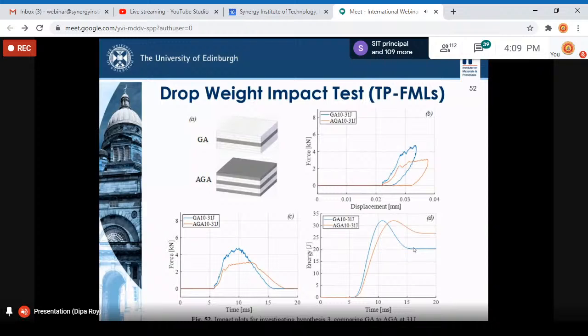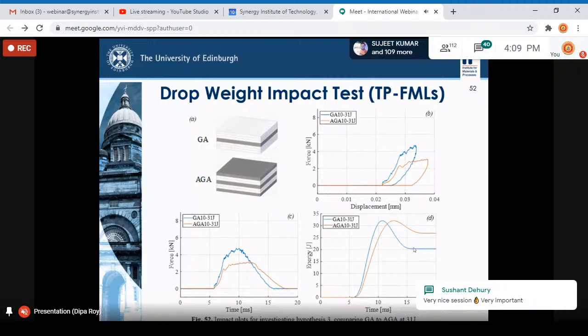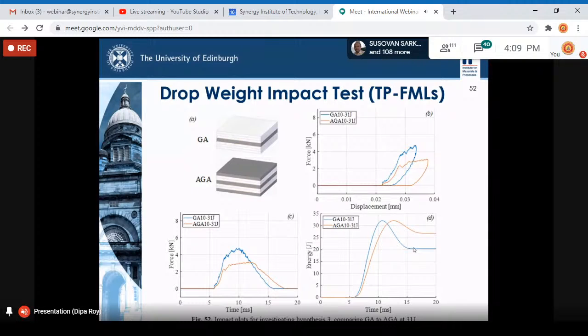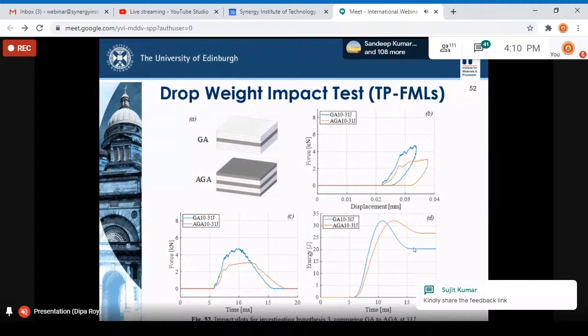It may be glass. We have done it with glass, but it is possible to use other fabrics like aramid or carbon. In the case of carbon, there might be a problem of galvanic corrosion because carbon fibers are conductive, which can be handled by putting a thin glass layer between the metal and the carbon composite layer. So there are a lot of opportunities here to combine different materials and different orientations, and we can get very different properties.